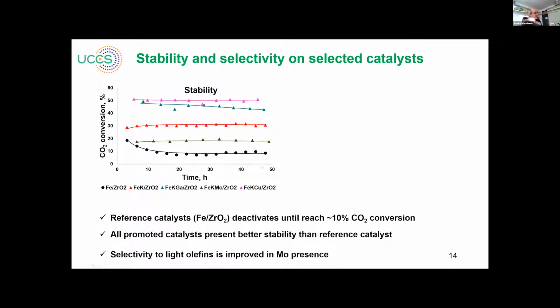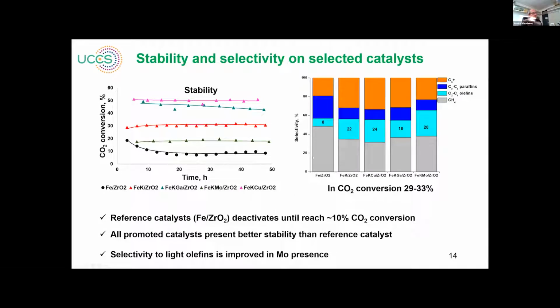On the next slide, we studied stability. We see that compared to the reference catalyst, so this is the reference catalyst for iron and zirconia, we have an increase in stability. The catalysts are getting more stable. And also, if we compare at the same conversion, 29–30%, under similar conditions, because it's important to have similar conversion, we have the highest selectivity on the potassium molybdenum catalyst. So the selectivity can be improved by addition of potassium and also addition of molybdenum. So that seems to be the best catalyst so far.